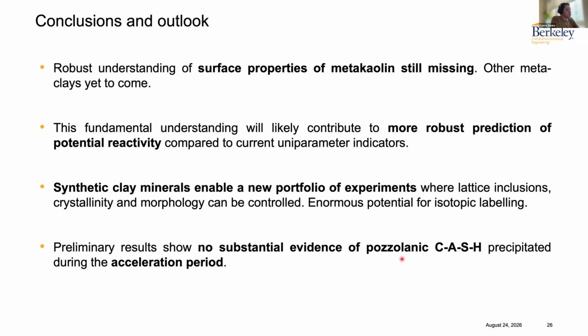Preliminary results also show no substantial evidence of pozzolanic CSH precipitated during the acceleration period in the systems that we have studied. So I think that's still an open question: is metakaolin really starting to react, explaining the quick slump loss that we see in these cements, or is there something else, once again surface mediated, that is taking place and explaining the changes that we observe?